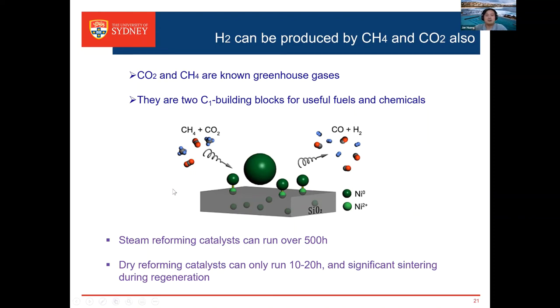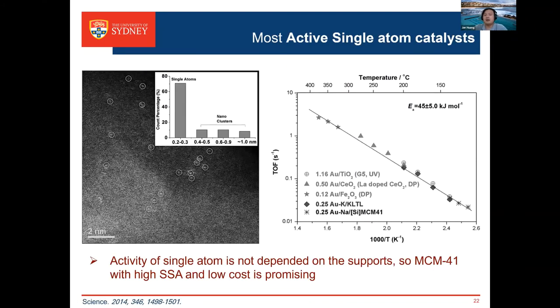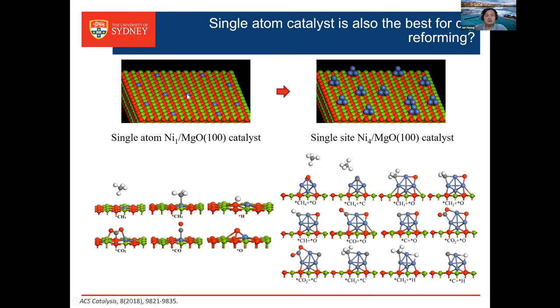But the challenge for this reaction is that the catalyst normally dies in 10 to 20 hours. But for steam reforming, if you use water, it can run over 500 hours. Therefore, we definitely need a very active catalyst to drive this reaction, because both molecules are quite stable. A few years ago, we developed a new type of catalyst. This is the most active single atom catalyst reported in the world. And we wanted to try it for this reaction. Unfortunately, it failed. A single atom is not working. But if we have four atoms together, then we are able to drive this reaction, because both molecules need active site dissociation.